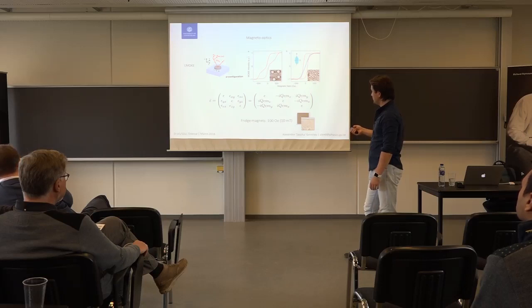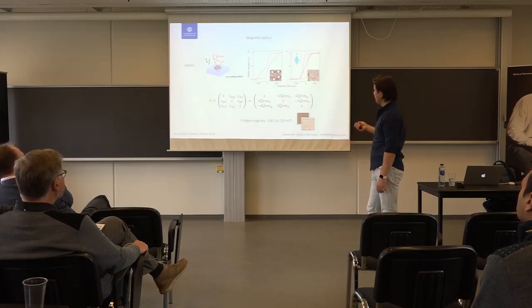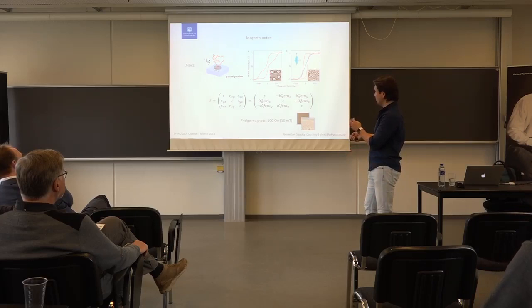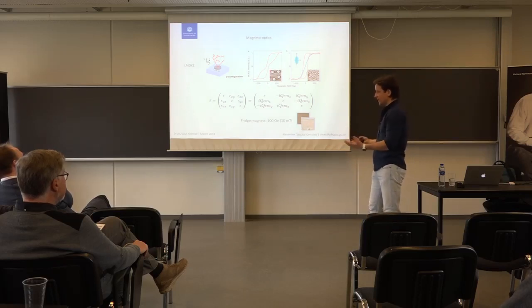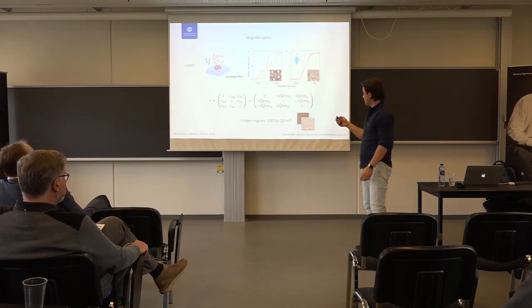So surely, all these intermediate points exist. This is real polarization rotation with the applied magnetic field. But certainly you would like to be somewhere here, because that's a static situation, so nothing is changing anymore. A slight variation of the magnetic field here will produce quite a substantial change in the polarization rotation. If you're sitting here, a couple of oersteds would create a big difference, and you don't want that for your functional system.